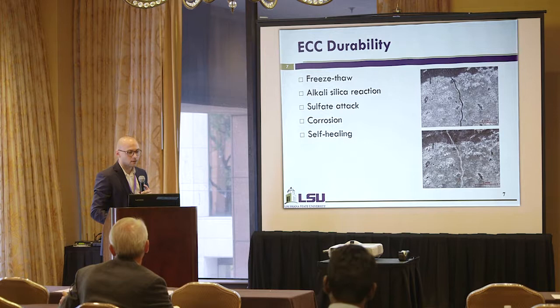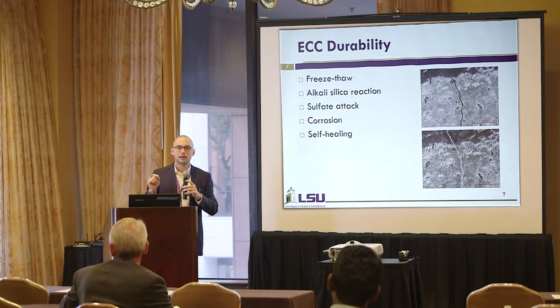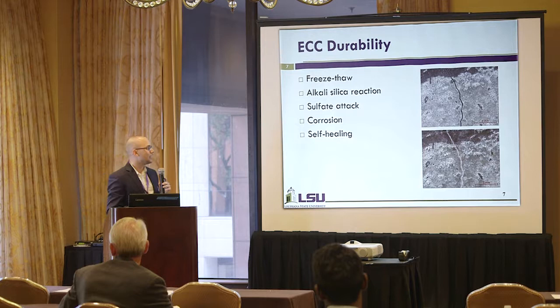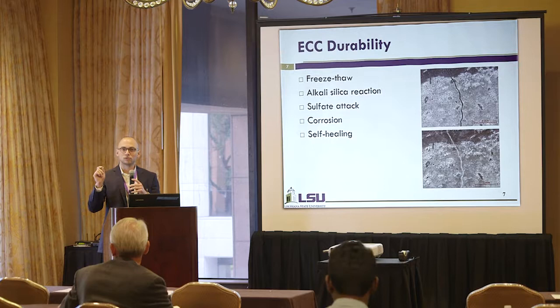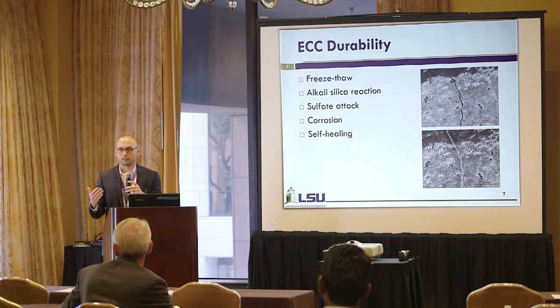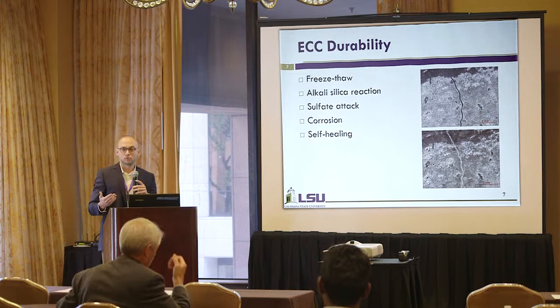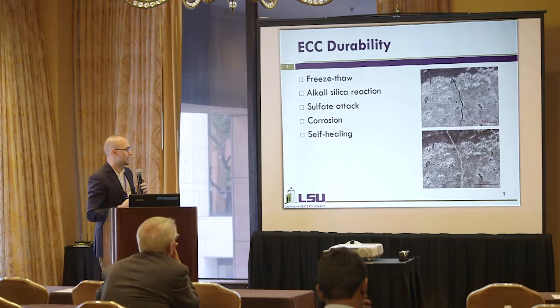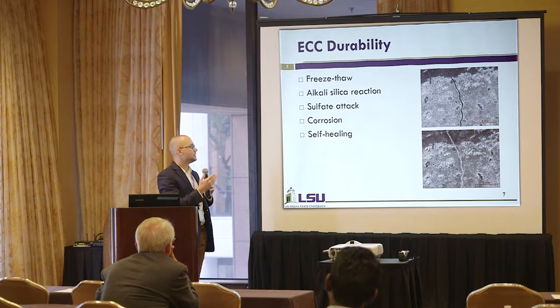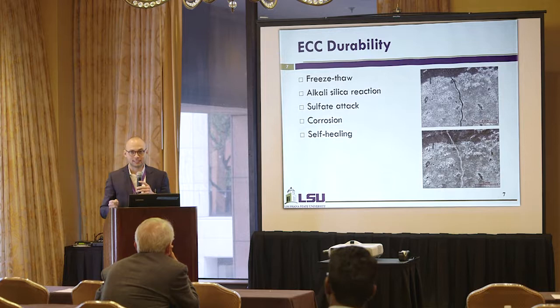Furthermore, ECC has great durability. The cracks formed in ECC, in contrast to traditional concrete, are really tiny — usually less than 60 micrometers. The literature refers to a threshold of 100 micrometers, below which cracks do not cause severe deterioration in concrete structures. Performance against freezing-thaw, alkali-silica reaction, sulfate attack, and even corrosion has been demonstrated through testing. ECC also exhibits self-healing: the tiny cracks allow the autogenous healing mechanisms of cementitious materials to take place and actually heal these cracks.